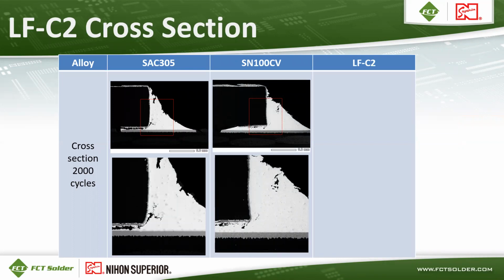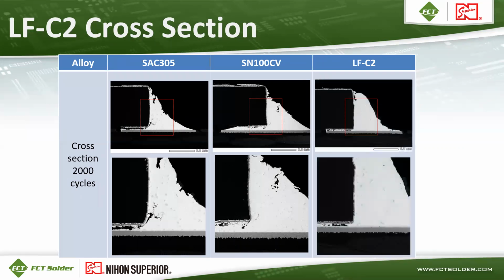SN100CV is in the middle, and you can see that there's some cracking there as well, but it's not as dramatic as for the SAC 305. And then for the LFC2, that actually has the least cracking shown on the right. You got a little bit of cracking between the component body and the board pad, but not much coming down from the top.